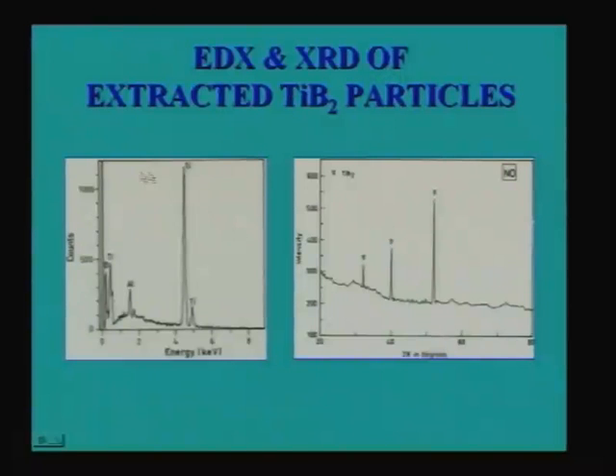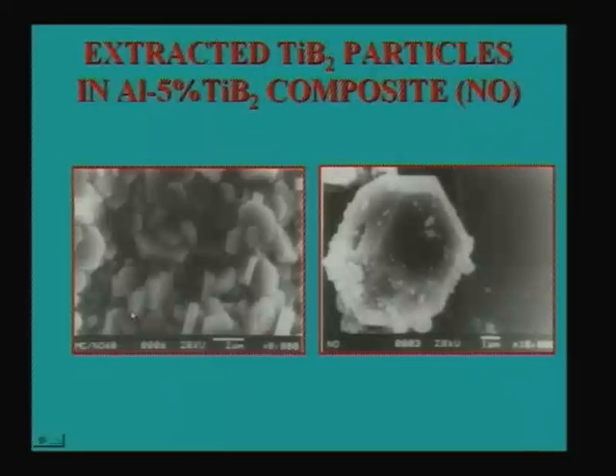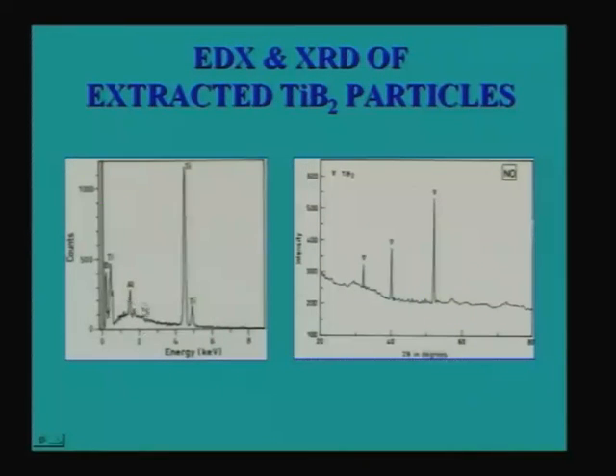So this is another SEM picture, SEM EDAX to confirm. This is from one of the extracted particles, which shows you the titanium and boron. If you carefully see, there is also a small amount of aluminum. This small amount of aluminum is possibly because, when you extract these particles, aluminum dissolves, but at the same time some aluminum probably sticks to particles like this, and that can give you a small EDAX signal, as you can see here. Otherwise it is mostly TiB2. One can do quantitative analysis from this spectrum and confirm that it is TiB2.